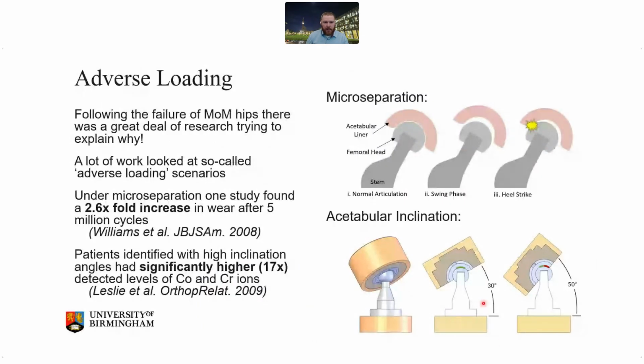Or acetabular inclination, where malpositioning of the cup or migration of the cup results in compromise of the lubricating film that generates as a result of articulation in these devices. So some of the work in the literature has found as much as a 2.6-fold increase on some of these things, significantly higher cobalt and chromium ions reported, I think this was in blood ion levels, as a result of these devices. So the wear isn't necessarily the be-all and end-all of the metric that's important for how these bearings perform.